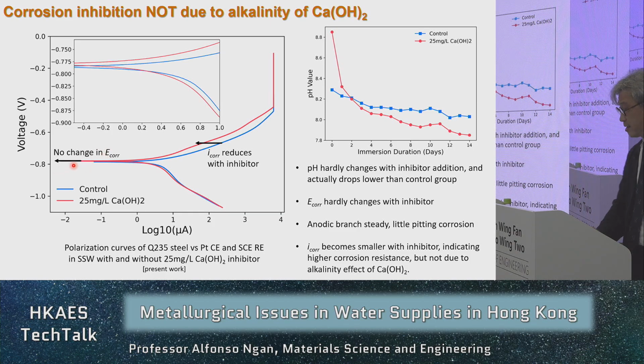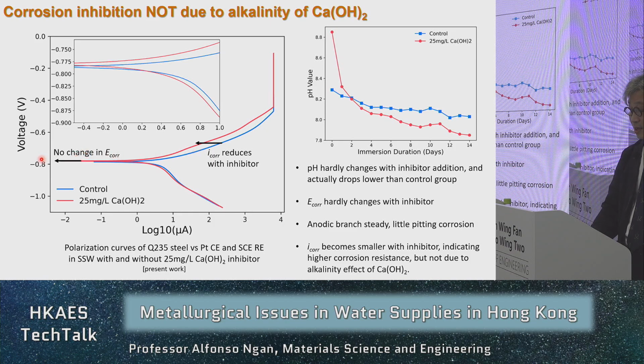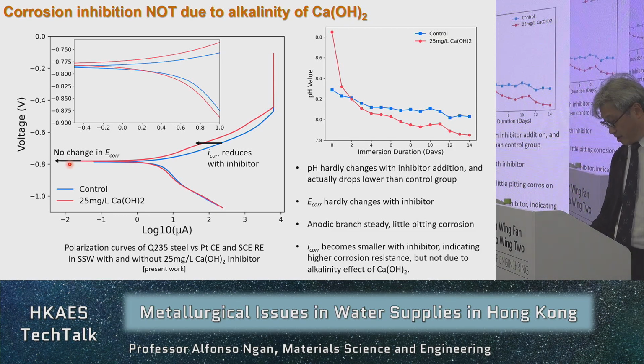And another way of seeing that is that if we look at the potentiostat or polarization curve, the red is with the inhibitor, the blue is without the inhibitor, and this tip over here, separating the anodic branch and the cathodic branch, this tip over here is what people call the corrosion potential, the Ecorr. You can see that for the two conditions, they have the same Ecorr. So in other words, the change is not due to a change in the corrosion potential. You do see that the corrosion current decreases after adding the inhibitor. So the corrosion no doubt slows down, but it's not due to a shift in the corrosion potential. So the pH cannot be a reason.